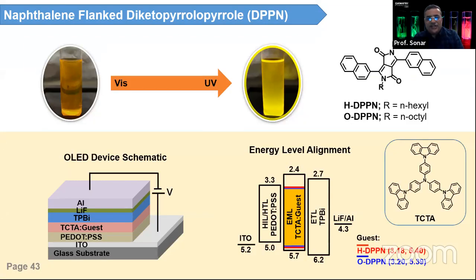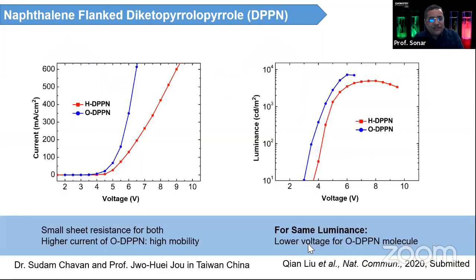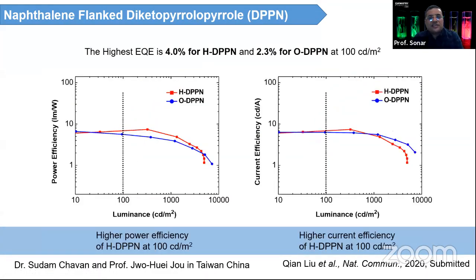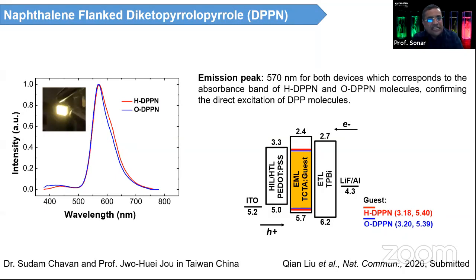Again, we did some light emitting diodes in collaboration with, I think, Sudham. Sudham has done some nice work on this when he was in Taiwan, and we made some OLED devices, and they operate at only 4 volts, hexyl substituted and octyl substituted. And here is the OLED, a small display you can see here. This is the geometry: ITO coated glass, PEDOT:PSS, and our material as an emitting layer, and then host TCTA guest. Our material as a host, and then we made this TPBi, and then we completed this device.